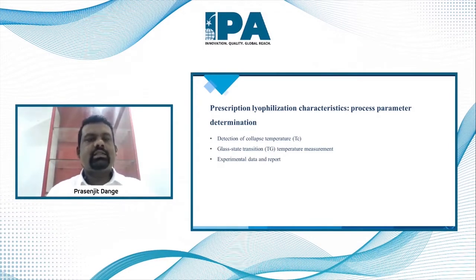For crystalline systems, the maximum tolerable temperature corresponds to the eutectic melting temperature. Only below this point is the system completely solid, but most freeze-dried formulations contain amorphous phases. In this case, the collapse temperature is very close to the glass transition temperature. In many cases, the collapse temperature is slightly higher than the glass transition temperature, and the difference between the two temperatures is very small. So it is very important to determine the collapse temperature and the glass transition temperature for any freeze drying formulation.